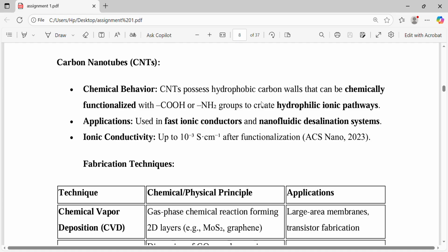Carbon nanotubes. Chemical behavior: CNTs possess hydrophobic carbon walls that can be chemically functionalized with carboxyl or NH2 groups to create hydrophilic ionic pathways. Application: used in fast ionic conductors and nanofluidic desalination systems. Ionic conductivity up to 10 to the power minus 3 per centimeter after functionalization.